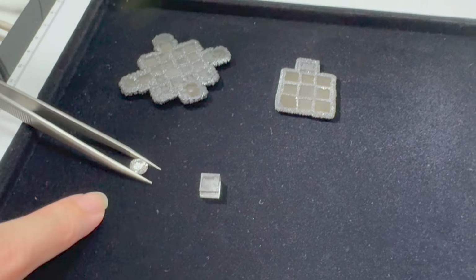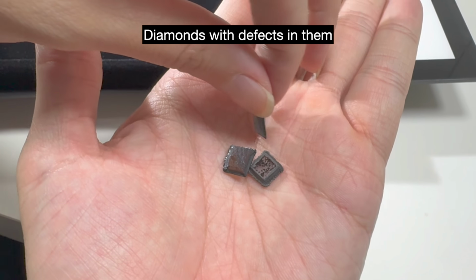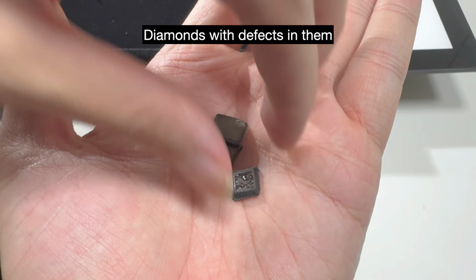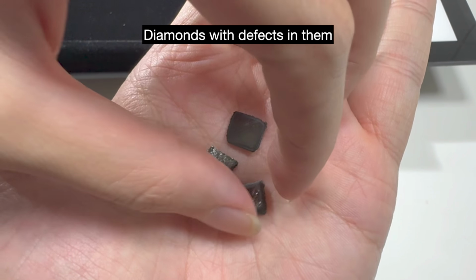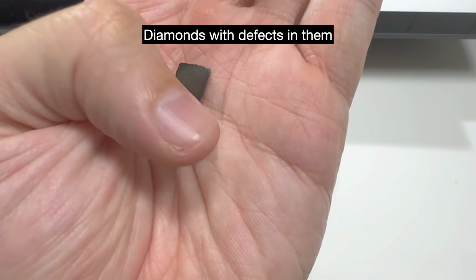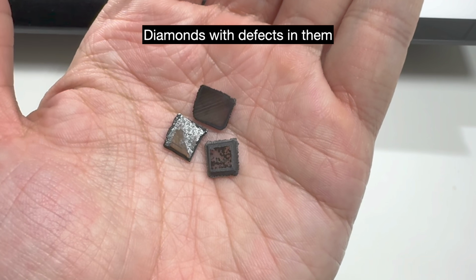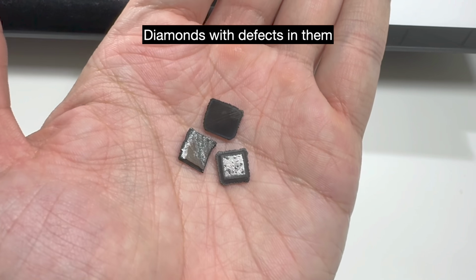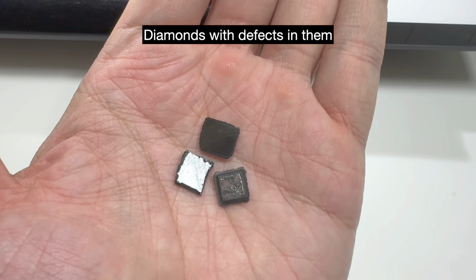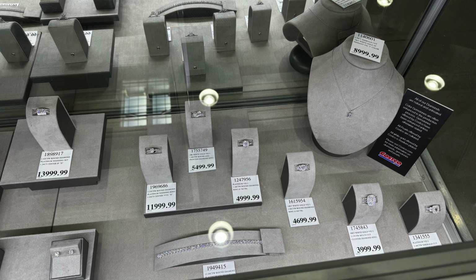Speed of growth, especially pure defect-free growth, remains an issue, but it is getting faster thanks to improved reactor designs. Furthermore, we can ameliorate this by growing diamonds in batches in parallel. Today, 2-carat diamond rings cost anywhere near $5,000 or so a pop in Costco. Costco mentions that all of their diamonds are quote-unquote natural, which I presume to mean mined. It implies that only mined diamonds are natural, but that should no longer be the case.